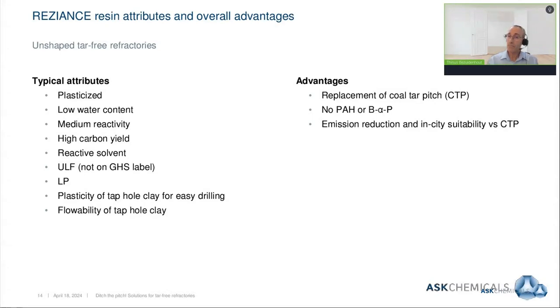You can tailor-make your reactivities by choosing a reactive resol of a certain reactivity. In our case, we often find that medium reactivity resols lend themselves very nicely to this application of tap hole clays. Of course, carbon yield is always important. For example, also in ramming masses, we consider reactive solvents again, and as mentioned before, the lowest possible free monomers in terms of free formaldehyde as well as free phenol.